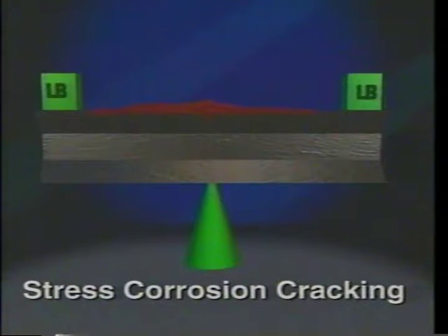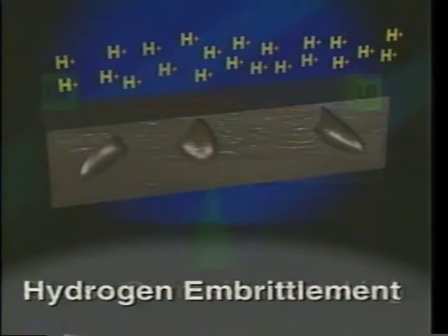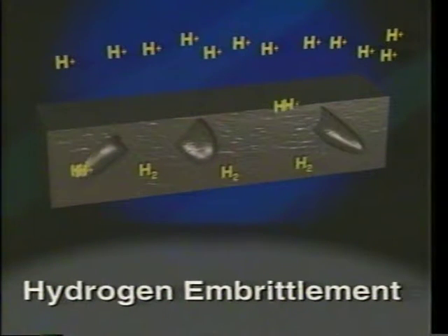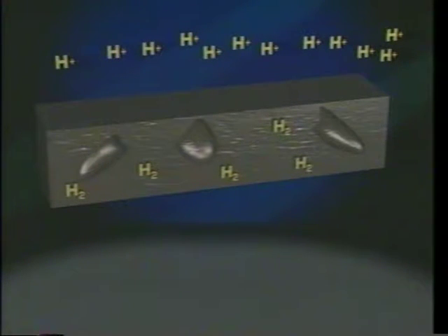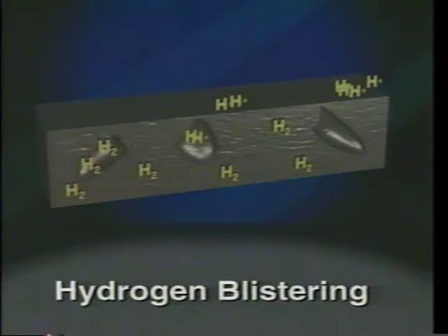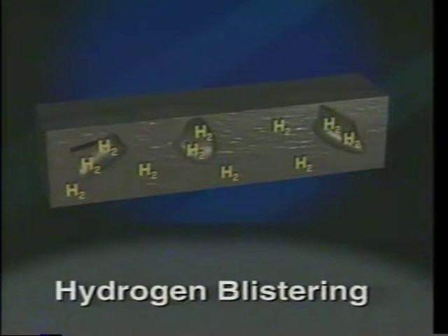Stress corrosion cracking happens when corrosion is accelerated by tensile stress. And hydrogen embrittlement occurs when hydrogen atoms on the surface diffuse into the metal and become hydrogen gas. The expansion of these gas molecules may cause the metal to become brittle and fail. If there is a void in the metal, the hydrogen gas molecules may concentrate in that area and cause hydrogen blistering. In addition, physical influences and temperature influences can accelerate the corrosion process.